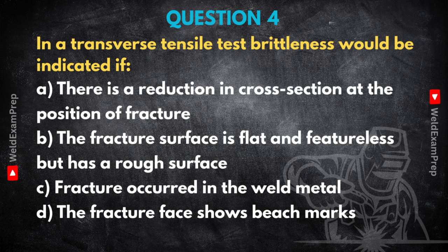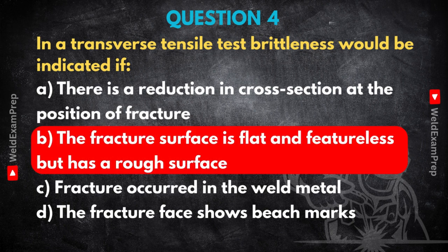Right. The key indicator for brittleness here is option B. The fracture surface is flat and featureless but has a rough surface. Flat and featureless but rough. How does that work? Okay, so when something breaks brittly, it fails suddenly with very little or basically no plastic stretching or deformation beforehand. Just snaps. Pretty much. Visually, that means the break surface looks flat. You don't see that necking down, that reduction in area you get with a ductile material stretching before it breaks. Yeah, right. The featureless part means you don't see things like shear lips or a cup and cone shape. But rough means, microscopically, the surface has this crystalline or granular texture because the crack just rips through the grains quickly. Cleavage fracture.